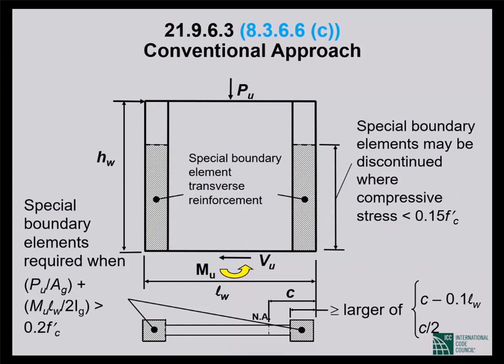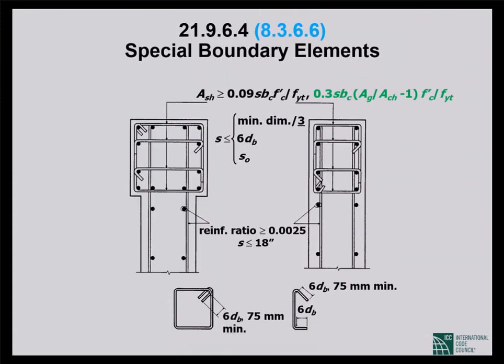Okay. So when that trigger goes off and we conclude that we must provide confinement over part of the shear wall section, horizontally, what we confine is the same as in the displacement-based approach. So it is 1/2 of the calculated neutral axis depth or the neutral axis depth minus 1/10 of Lw, whichever is the larger of the two. So even when we are using the conventional approach, we will have to calculate neutral axis depth. That does not go away. Vertically, we will discontinue the special confinement only when the combined compressive stress under Pu and Mu drops below 15% of f'c, as I have said multiple times already.